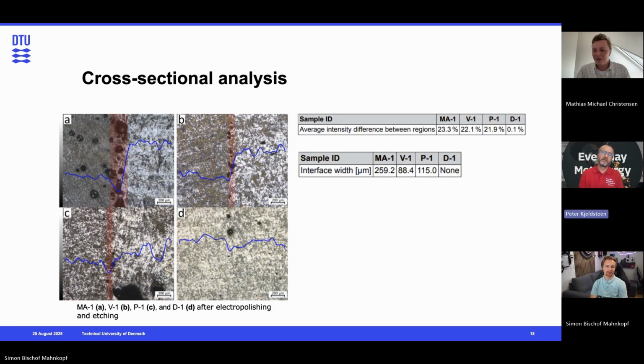No, I could imagine. If you heat it up, the remaining austenite will be transformed to martensite. Actually, with thermal heating afterwards, if you don't go too high in temperature, you could actually stabilize the austenite a bit, because what happens here is once we print it, we use the strain to create the martensite. So we always have some strain in the parts, and the more strain, the more martensite. And when you anneal it afterwards, the austenite gets more stable as you remove the stress, and you have a larger threshold for when you move into the martensitic zone.